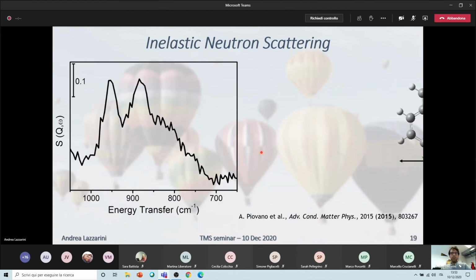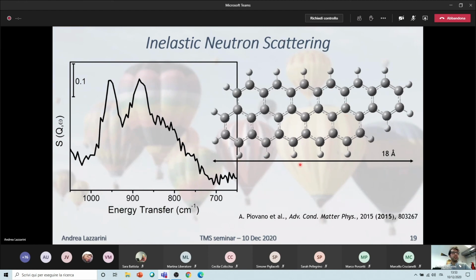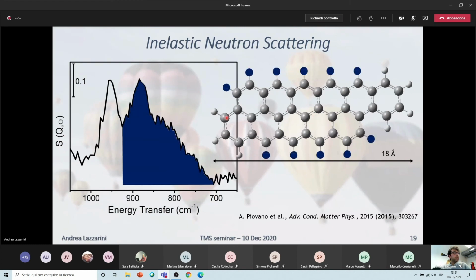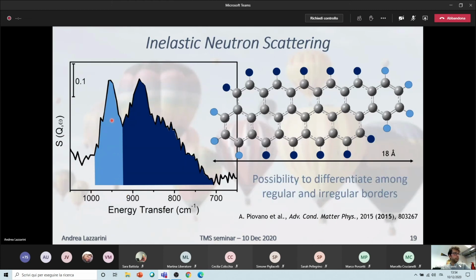So we simulated, for example, a small fraction of condensed aromatic rings that can be, let's say, compared to one of these sheets made of benzene rings. We found that this kind of signal was given by very regular borders, while the signal coming at higher energy was fundamentally coming from more disordered borders. Therefore, by comparing the relative intensity of these different bands, we could have an idea of which kind of carbon was more regular or irregular on the surface.